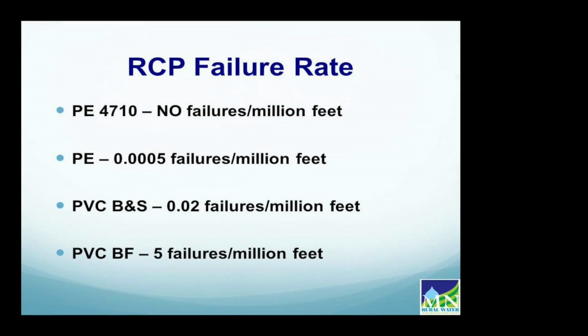These are some of the failure rates we discussed with the PE 4710 materials, based on the critical pressure that's been determined, 3 times the pressure rating. RCP will never occur in a PE 4710 material. For the earlier generation polyethylenes, we estimate the failure rate is about 0.0005, a very low failure rate. For PVC joined by bell and spigot, it's a little higher, 0.02 failures per million feet. But here the crack only travels a few feet. And for PVC joined by butt fusion, the failure rate over the last few years has been about 5 failures per million feet of pipe.